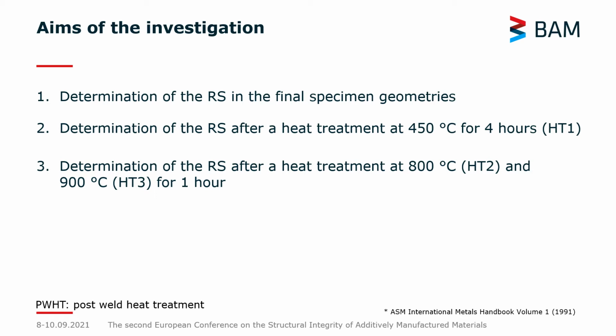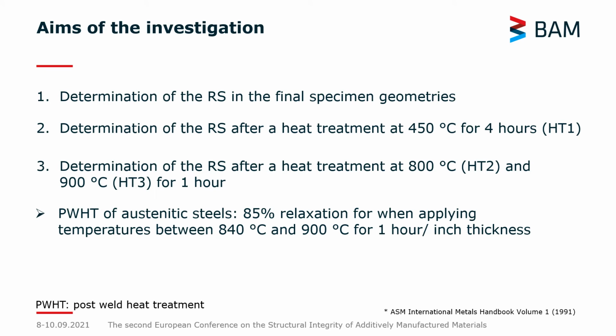Why are we interested in these temperatures? In fact, we know from post-weld heat treatment of austenitic steels that when we apply 840 degrees to 900 degrees for 1 hour per inch of thickness, we can obtain an 85% relaxation. However, we know also that welded austenitic steels, from a point of microstructure, how the residual stresses are distributed, is all very much different to the laser powder bed fused material. And we aim at understanding whether this kind of heat treatment can be applied to our laser powder bed fused material.